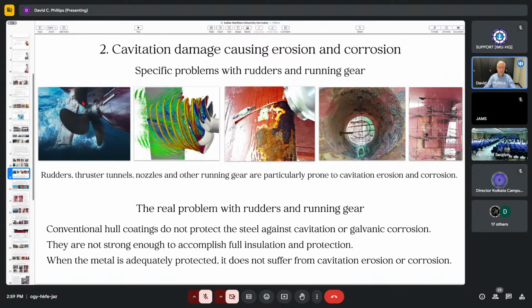You get turbulent fluids, like behind a propeller, for example, create cavities or bubbles in the water. When these hit the steel surface, they explode, or they implode actually. And they implode with extremely high temperatures and pressures. It's a very strange phenomenon, but there it is. You see the results here. These bubbles, which is all that is, have completely removed the hull coating, then they've pitted the steel, and the steel is corroding like crazy underneath. And that's after 5 years with regular hull coating. And you see they've even got a sacrificial anode here, and it hasn't helped it.